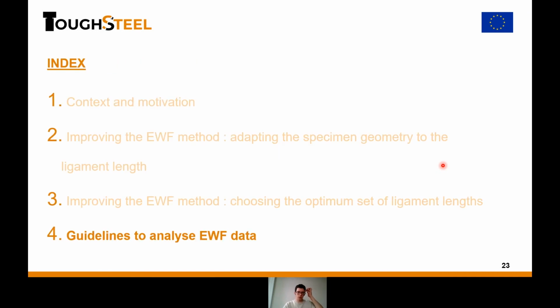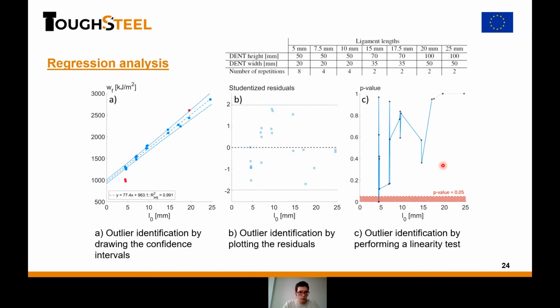Okay, last thing I would like to show you is how I analyze my experimental data. I will show you a typical example here. This is for stainless steel 304L. Here you have the specimen dimensions and the number of repetitions. And you see, like I was saying, I stacked more samples with lower or smaller ligament lengths and only a few with larger ligament lengths.